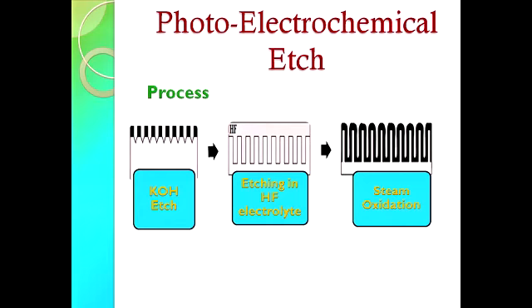And the next method that can be used to form the thick silicon dioxide layer is the photoelectrochemical etch, in which the first process we form V grooves by using KOH etch because they're selective in this direction. And this is mainly done to initiate the etching of HF electrolytes. And this is followed by steam oxidation, which forms completely thick silicon dioxide layer.